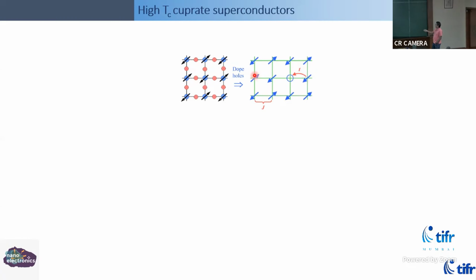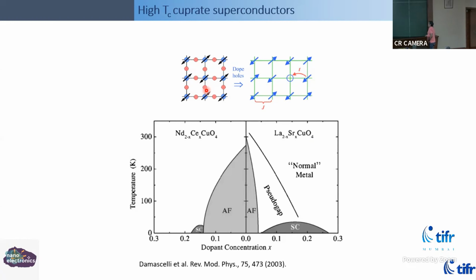So you have a copper oxygen plane which forms this square lattice, and there you have antiferromagnetically aligned states. At the parent state, it's an antiferromagnetic insulator with no availability for electrons to hop from one site to another, which is a peculiar state for a mother state from which superconductivity arises, because you have seemingly an insulator. But there are now other experiments in systems like moiré twisted graphene that are providing some insight, maybe not directly connected to the origin of this superconductivity, but that's for some other day. So the phase diagram of high temperature superconductors is very complex.